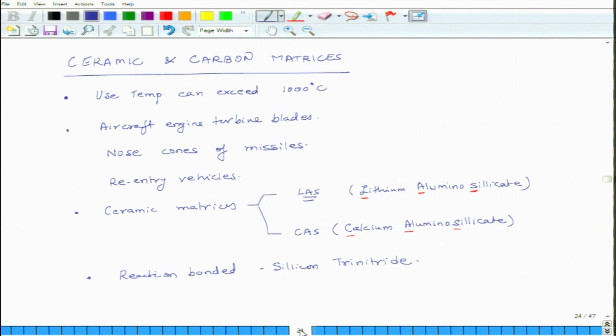And the last point about ceramic materials is you can use these materials with fibers. So, there is no point in using these ceramic materials if the fiber breaks down at low temperatures. So, the real value of these matrices comes in when you use these matrices with fibers which can handle high temperatures. So, a lot of times they are used with silicon carbide fibers. So, you have a carbide fiber and you have a ceramic matrix, and the overall product is really high temperature resistant. Next, we will look at carbon based matrices.